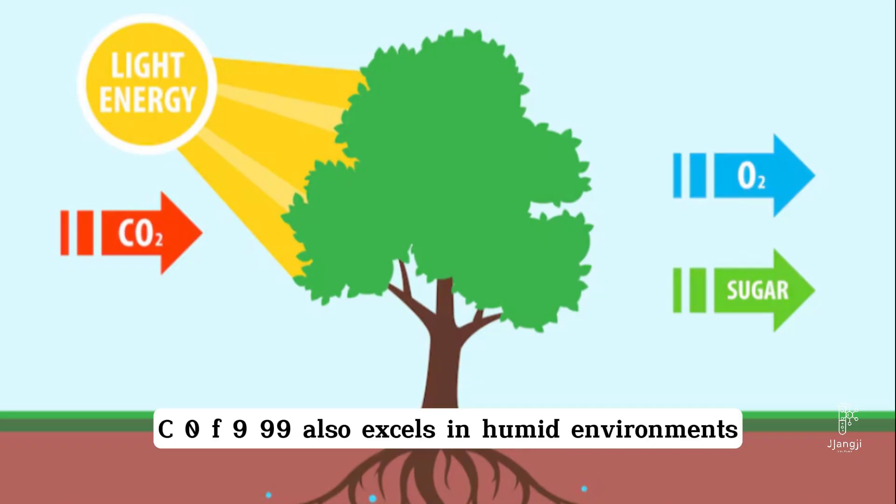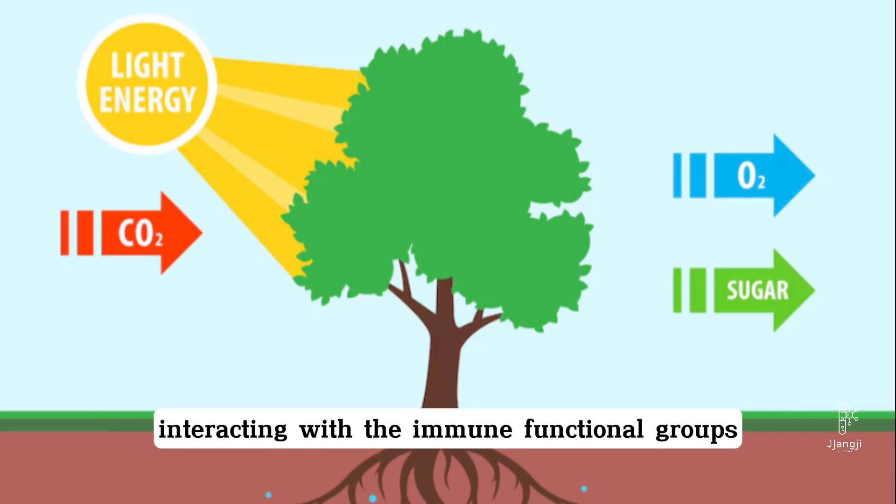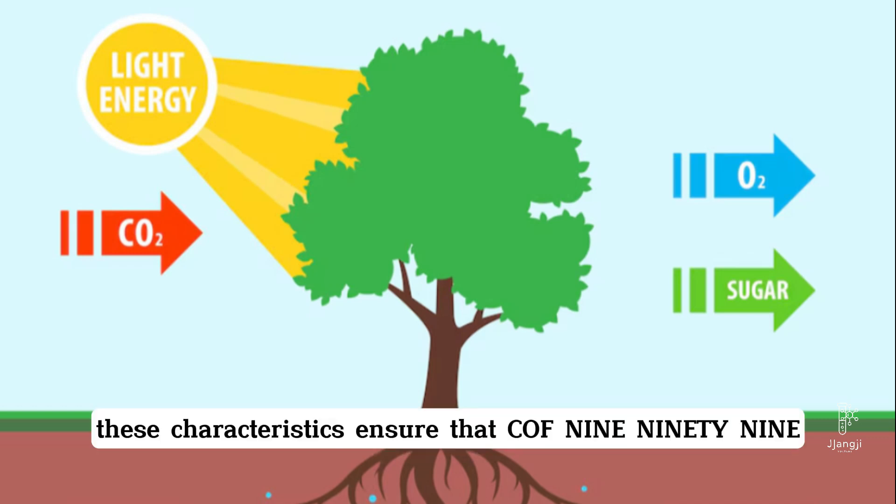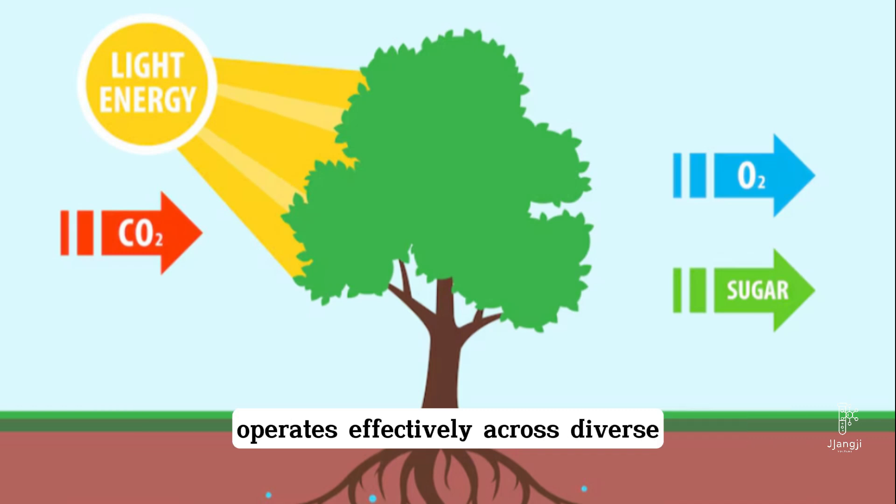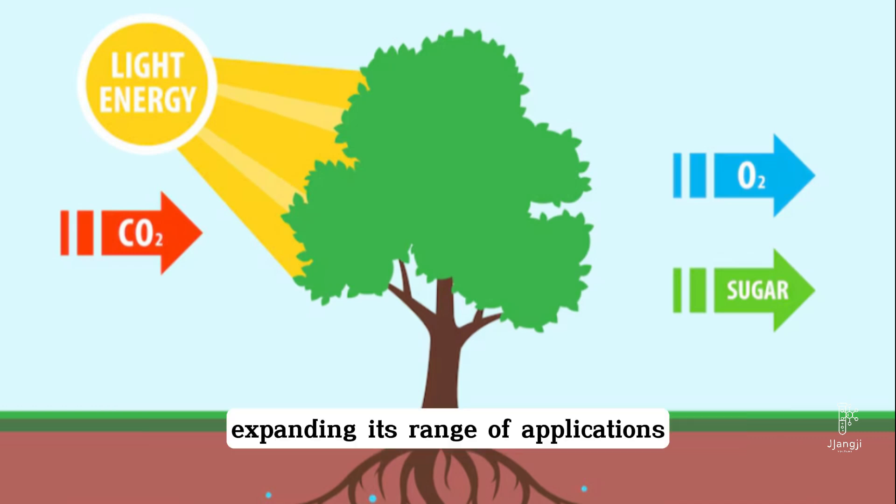COF-999 also excels in humid environments, capturing nearly twice as much CO2 under 50% relative humidity compared to dry conditions. This enhanced performance is due to water molecules interacting with the amine functional groups, increasing the reactivity of CO2. These characteristics ensure that COF-999 operates effectively across diverse atmospheric conditions, including high-humidity regions, expanding its range of applications.